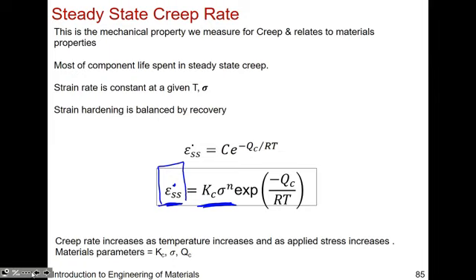These are materials parameters that you're either given because you've tabulated this sort of information. And so you could calculate the power law, the exponent of the stress that's applied. And so you know if you apply a certain stress, sigma, what the strain rate is going to be. This is particularly useful when you're trying to accelerate failure and fatigue, actually. So if you know at a certain temperature with an applied load what your steady state creep rate is going to be, you could extrapolate that to what happens when I experience creep at a higher temperature or for a longer period of time. So accelerated failure analysis is quite useful when you know these things.